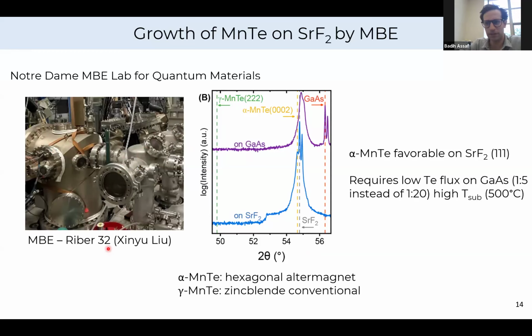And one aspect that's important to control here for manganese telluride is the crystalline phase that it nucleates under. Gamma MnTe, zinc blende MnTe, has been studied extensively in the past, and you want to tune your growth parameters to actually avoid nucleating this phase and preferentially nucleate the alpha MnTe phase. There are tricks to do it on each substrate, but it turns out that on strontium difluoride, alpha MnTe is more favorable and just grows for a very wide growth parameter window.